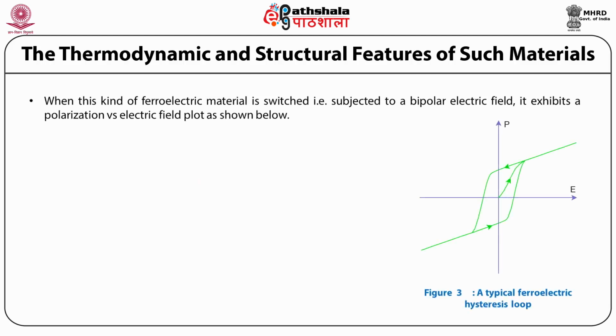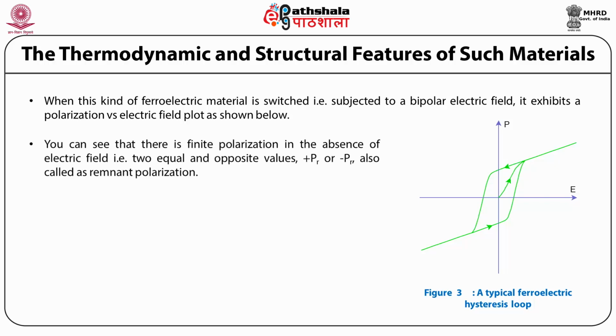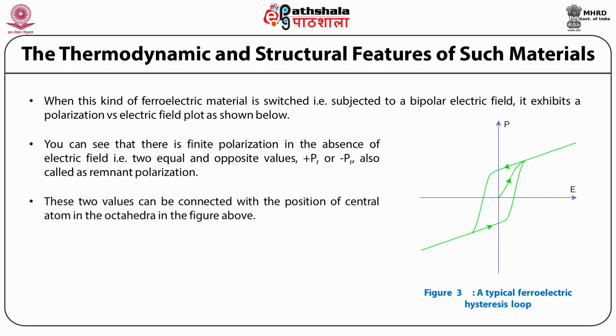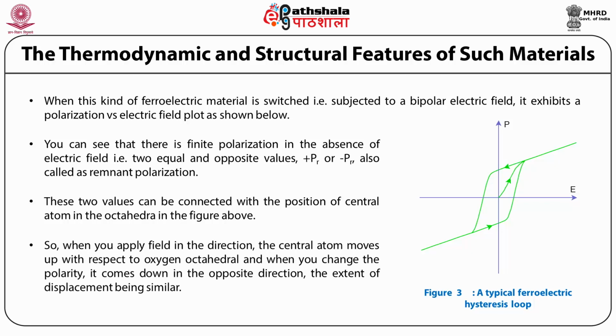minimum. When this kind of ferroelectric material is switched, that is subjected to a bipolar electric field, it exhibits a polarization versus electric field loop, which you can see in this figure. You can see that there is finite polarization in the absence of an electric field, that is two equal and opposite values, plus Pr or minus Pr, also called remnant polarization. These two values can be connected with the position of the central atom in the octahedra in the figure shown. So when you apply a field in one direction, the central atom moves up with respect to the oxygen octahedra, and when you change the polarity, it comes down in the opposite direction.